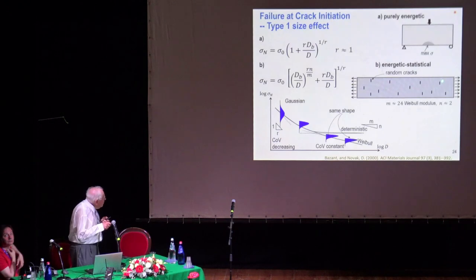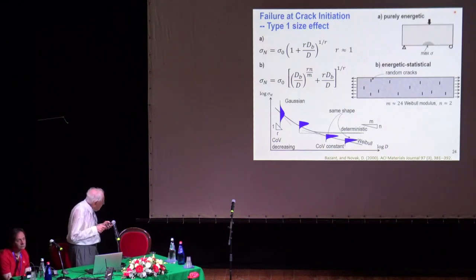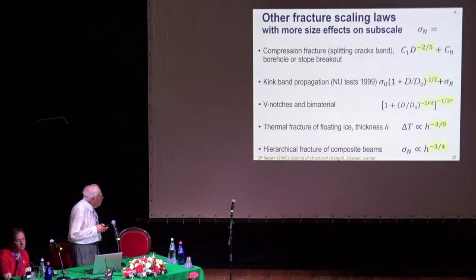And if you have a large zone of uniform stress, cracks can form randomly at many parallel locations. Obviously, the weakest link model goes to Weibull statistics. So it ends up with a slope. So these are deterministic formulas. This is a formula going to Weibull behavior. R is an empirical exponent. m is the Weibull modulus, which is infinite for this case, no probability. And also, the distribution changes from Gaussian to Weibull distribution.